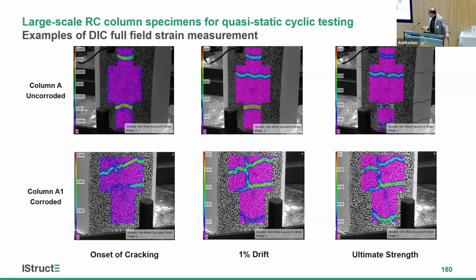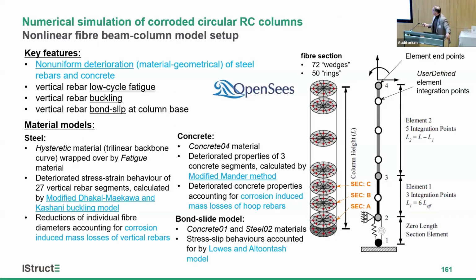So this was the experiment, but the most important part is this bit, to be able to model this. These experiments are benchmark experimental tests that we normally do, but we want to model them. So we use a lot of material models that we have tested over the past few years in the fiber-based model. These are essentially nonlinear beam column elements. In each element, we have different integration points, and at each integration point we have a cross section. And based on the moment curvature response of the cross section, we can integrate across the element to get material nonlinearity.